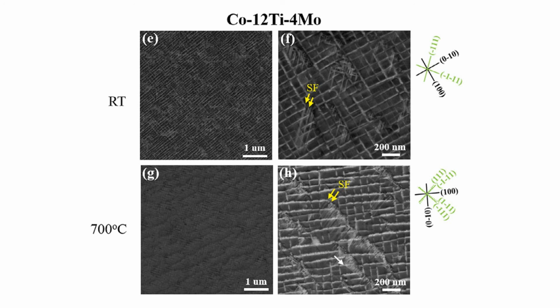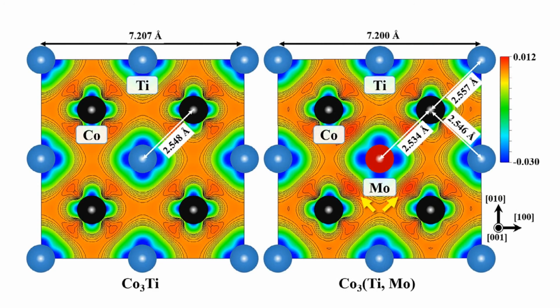The molybdenum-added alloy exhibited an enhanced compressive yield strength and strain hardening behavior as compared to the reference binary alloy. This behavior was attributed to a 25% larger gamma prime volume fraction and to the 7% higher planar fault energies in the cobalt, titanium, molybdenum material.